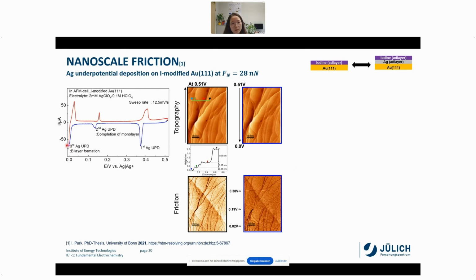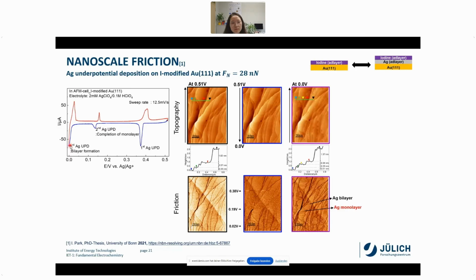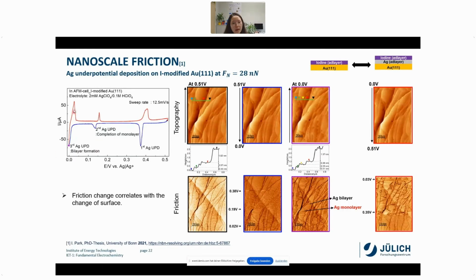Then when the potential was kept at the third UPD peak, topography and friction show some incomplete layer, and friction shows additional information that the bilayer has lower friction compared to that on the monolayer. And then when the potential was swept back to the initial potential, as we saw in the blue image, topography shows no meaningful changes, but the friction shows that the surface is changing by sweeping the potential. So it indicates that friction change correlates with the change of the surface. So by measuring the friction we can know how the surface is changing.